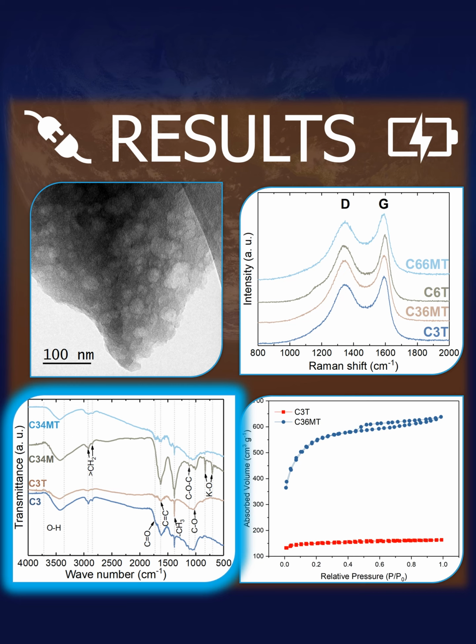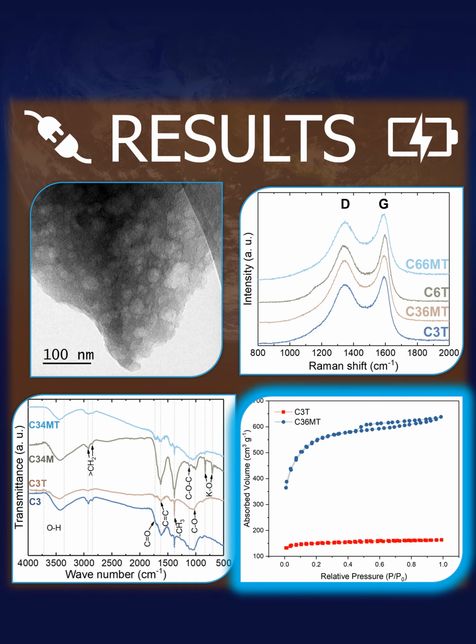In the FT spectra, we found the potassium anchored in the surface of our materials, previously to the heat treatment. This indicates that we have a good process for forming pores in the material. In the isotherms, we can see the difference between base carbon and the activated carbon, and how the surface area increases after this activation.